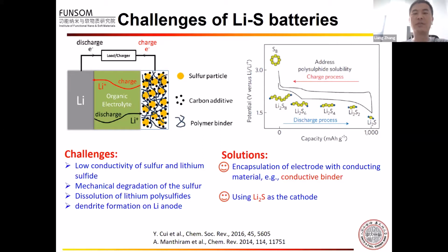So although lithium-sulfur battery is very promising, there are some challenges. For example, the low conductivity of the sulfur and the lithium sulfide, and the mechanical degradation of sulfur during the discharge and charge process. In addition, the intermediate lithium polysulfide has a very high solubility in the electrolyte, which can induce the so-called polysulfide shuttle effect, which is not good for the cycling performance of lithium-sulfur battery. In addition, for the lithium-sulfur battery, we use lithium metal as an anode. Therefore, the lithium can form lithium dendrite, which can induce a short circuit of the lithium-sulfur batteries.